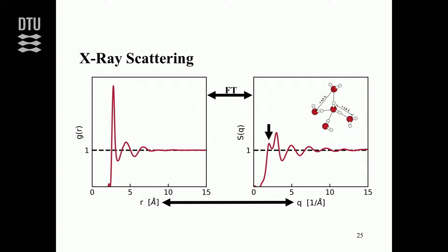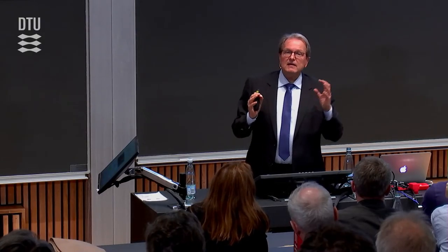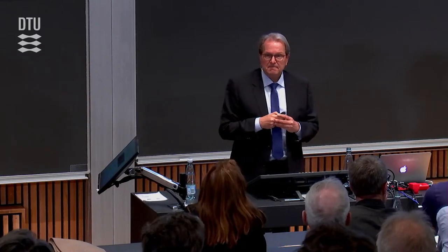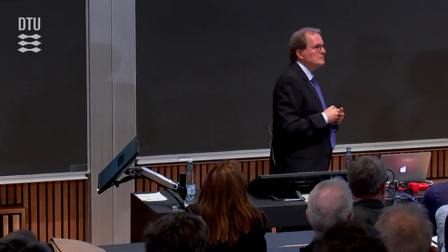Of course, in water there are also the more isotropic interactions, which we think about as dispersion, van der Waals interaction. So you could think about it a little bit like the low density is more governed by the directionality of the hydrogen bond, but the high density starts to pick up a little bit more of the dispersion, the more isotropic interaction. So you can move in another water molecule, not 12 nearest neighbors, but maybe going from 4 to 5 and 6. But the extra molecule will be at a little bit longer distance than the nearest neighbors here, so to speak. Yeah. Thank you.